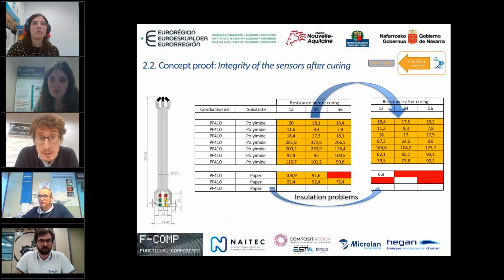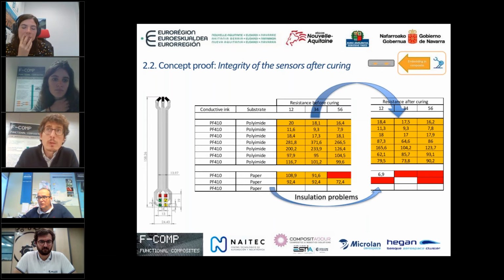Another check that was done, apart from the mechanical ones, were the functional ones. In here, what we saw is that if the ink in the sensor is not completely cured before putting the sensor in the oven for doing the composite, it gets cured inside the oven. This has an issue because the ink is covered with the electric fiber, and so the curing process is not very good. So what we see is that there is a degradation in the resistance, but we don't get to the proper resistance. So this is something that we have already solved. We have seen how to do that, but we realized that it's important to have, for an escalation of this process, a very adequate curing of the sensor before putting it in the oven.